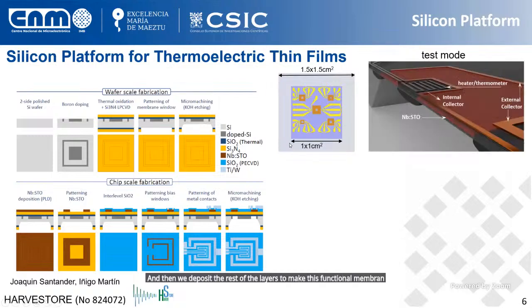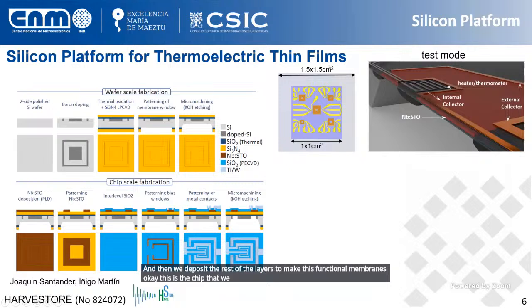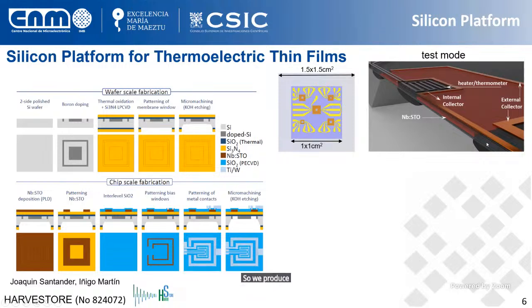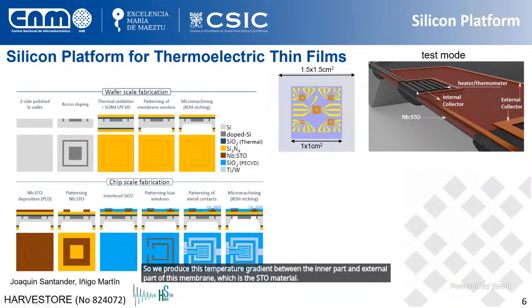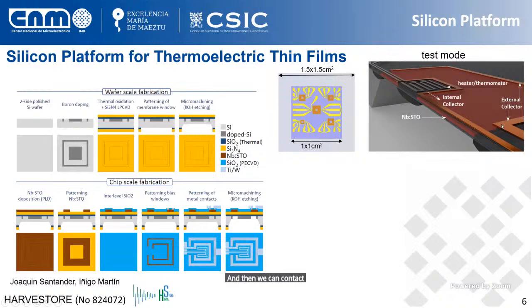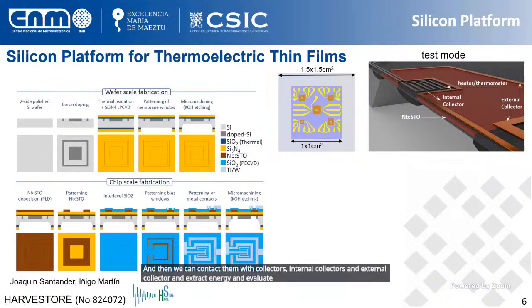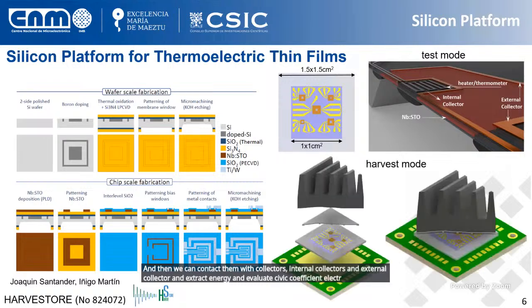This is the chip that we are developing so far, which is a 1.5 by 1.5 centimeter square, and in between we have 5 membranes which have an integrated heater for test purposes. We heat the central part of the membrane, and we externally produce this temperature gradient between the inner part and the external part of this membrane, which is the STO material. And then we can contact them with collectors, the internal collector and the external collector, and extract energy and evaluate Seebeck coefficient and electrical conductivity of these materials.